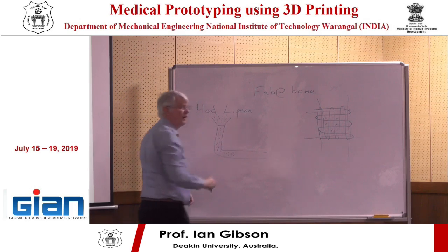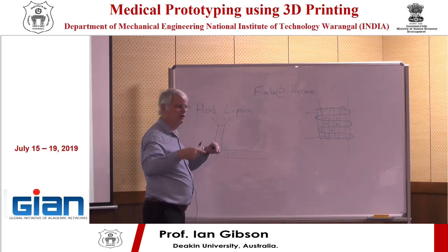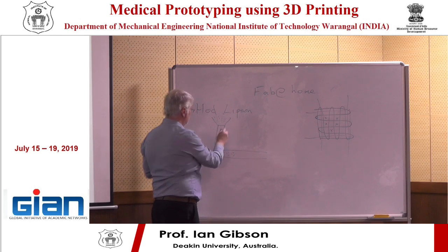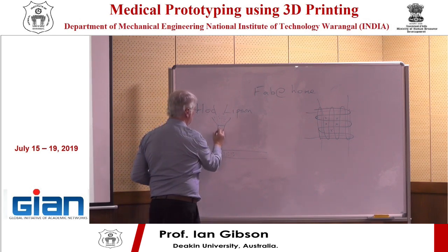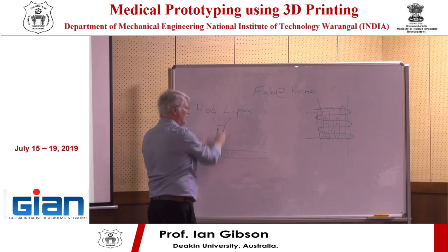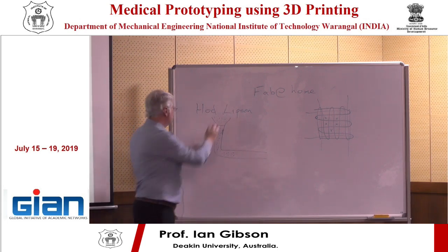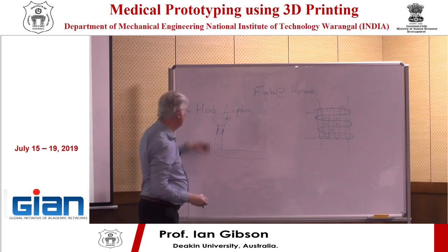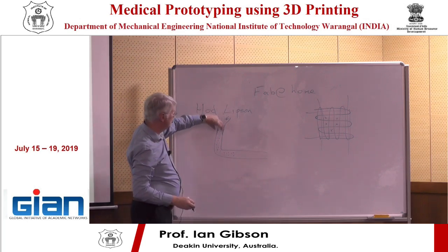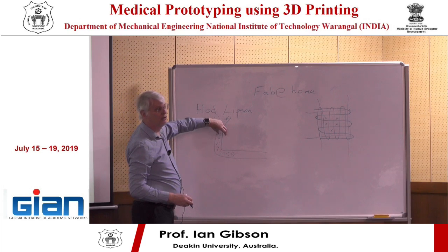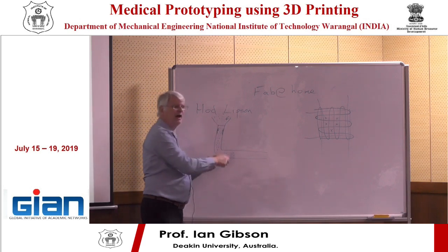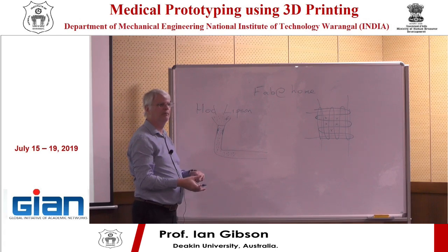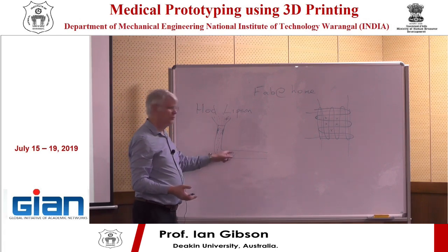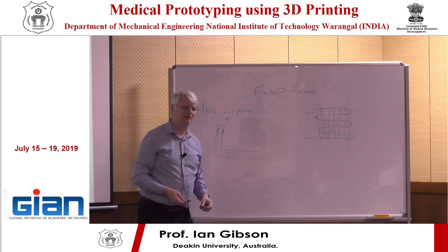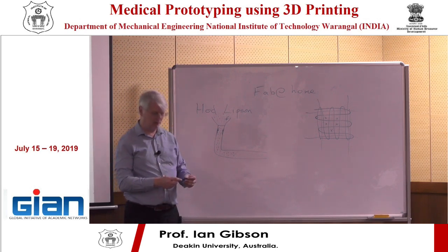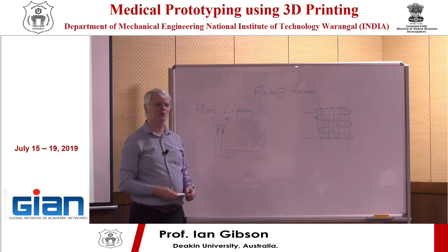And because of shear effects and shear turbulence in the channel, you'd have little micro vortices here, which basically allow you to extrude. This is outside of the nozzle. You would not get the particles at the surface of the scaffold. So the TCP might be bioactive, but it's no use because the cells don't see it. The cells won't detect it.